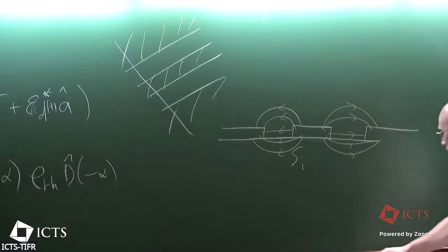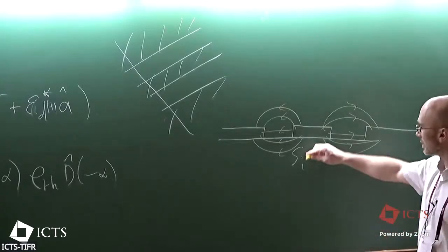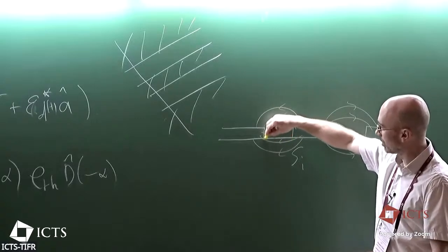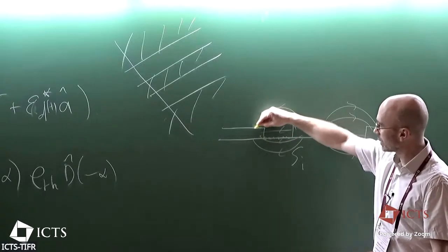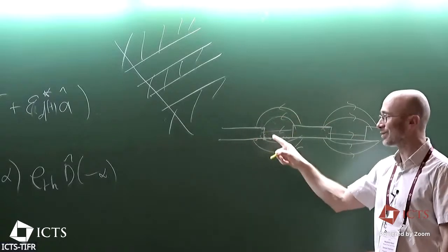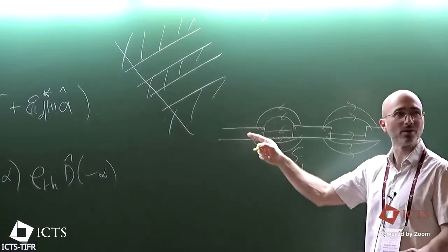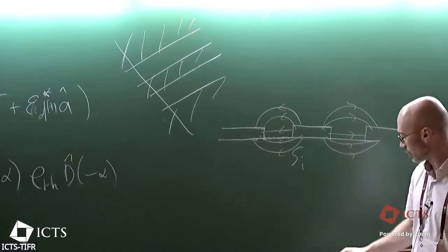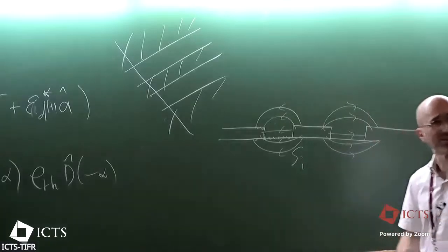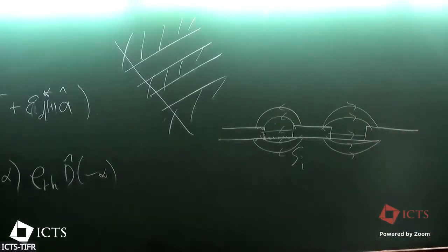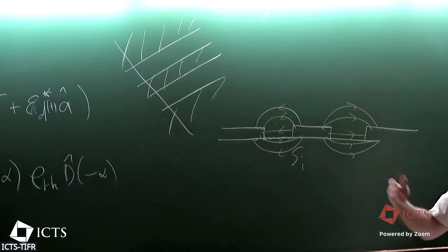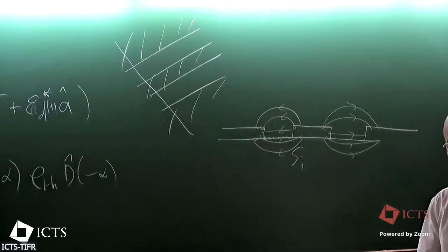But what really is bothering us is the fact that these fields have a participation of all the defects, all the material that we didn't clean well enough on the interfaces. So these are the mostly annoying ones. In 3D it's very different because most of the field is in a big volume of vacuum, and so the quality factor is better.